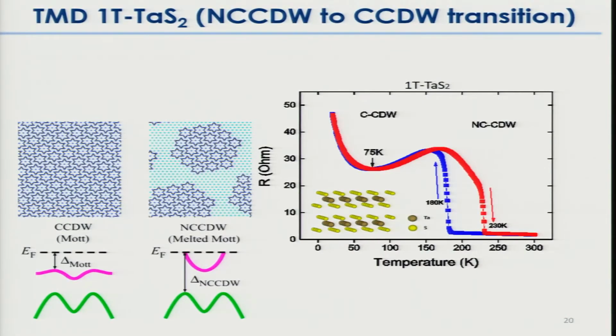Okay. Let's look at tantalum disulfide. This is a fascinating material. This is a charge density wave material. This is the resistance as a function of temperature of tantalum disulfide. It exfoliates beautifully. It's a layered compound, a van der Waals crystal. It's a non-commensurate CDW above these temperatures. This is a cooling transition. This is a warming transition. It's a first order phase transition.